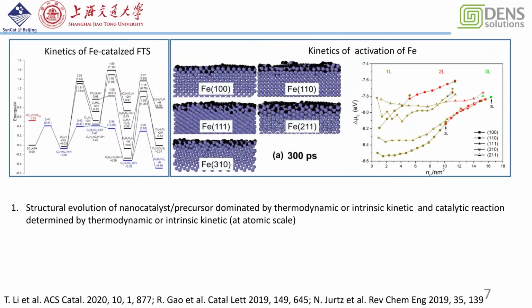So why is it very limited? Because we also have limited knowledge about the catalytic reaction. The above is Fischer-Tropsch synthesis. The left side is the kinetics of the Fischer-Tropsch synthesis, but the right is the kinetics of the activation of the catalyst. So we can see that something is very different. The catalytic reaction happens on different facets and different steps. We can use theoretical calculations to understand the energy of the intermediate compounds. But by using in-situ TEM technology, we directly see the activation of the catalyst, not the catalytic reaction.